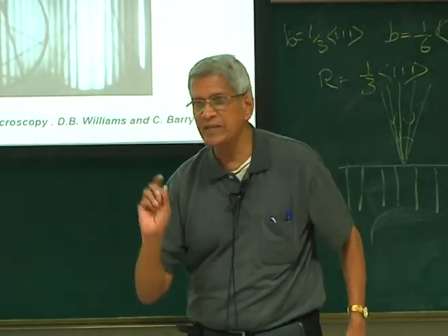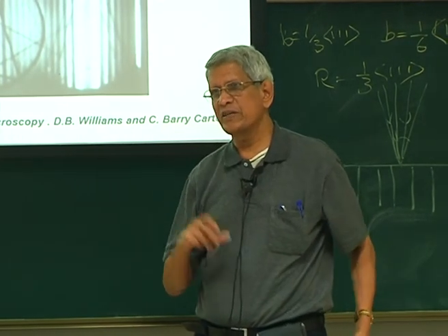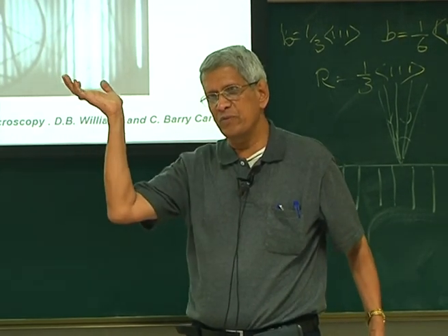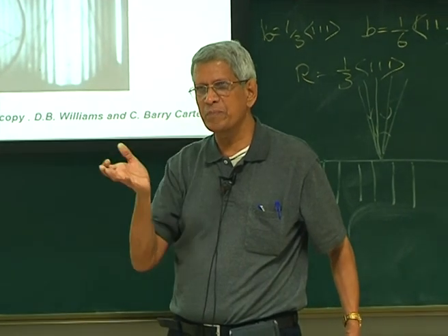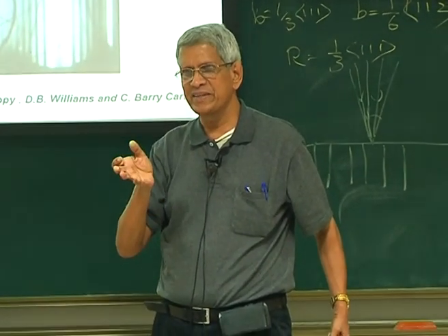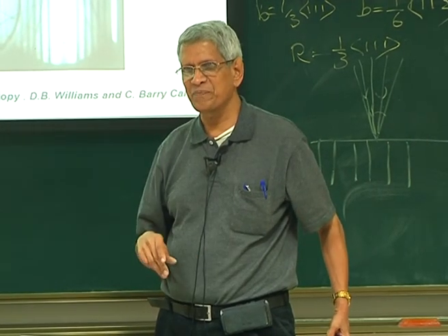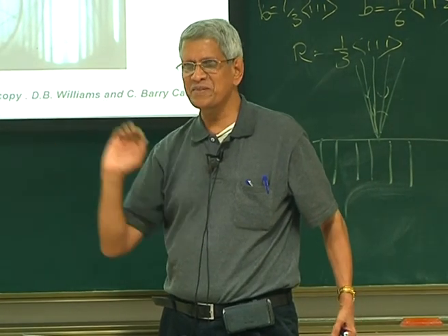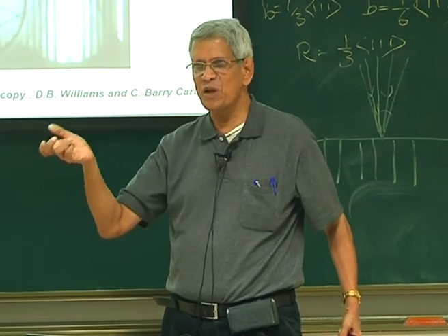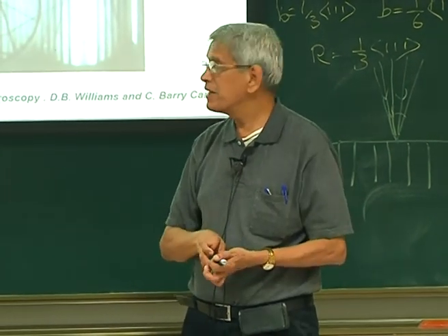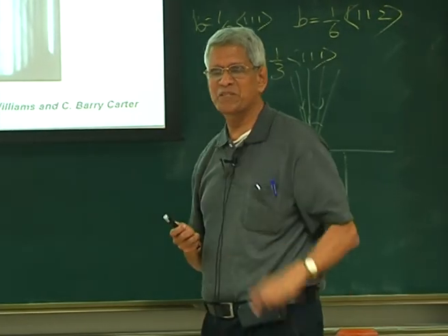What is the variation in S when it happens? We saw that in a foil which is wedge shaped, if the thickness varies, S remains constant, then that gives rise to a fringe contrast. Similarly, if the thickness remains the same, and S varies, a similar effect should happen. That is precisely what happens in the convergent beam diffraction.